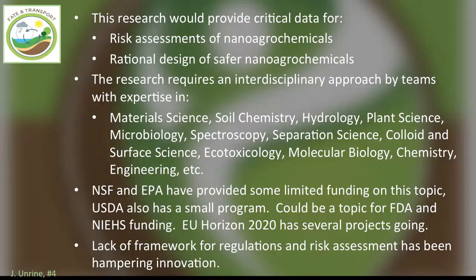We have significant analytical challenges. We've done well with inorganic nanoparticles, developing methods to detect them at parts-per-quadrillion levels using single-particle mass spectrometry. But for soft nanomaterials made of polymers — which are probably mainly what will be used in agrochemical formulations — we have significant detection challenges. We also need an inventory, as there's no way to know which products contain nanomaterials without examining them under an electron microscope. This will feed into risk assessment and the rational design of safer, more sustainable materials.